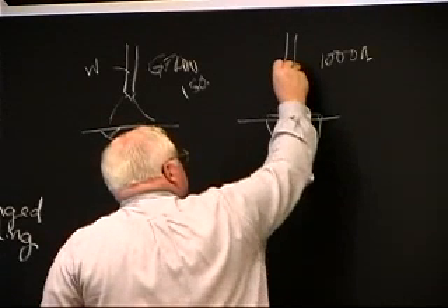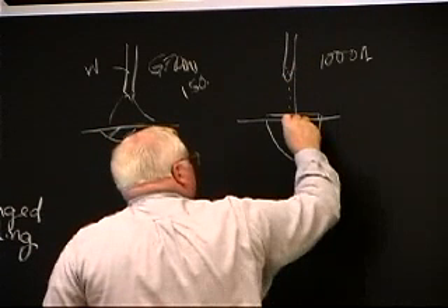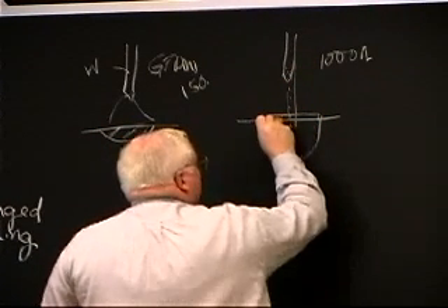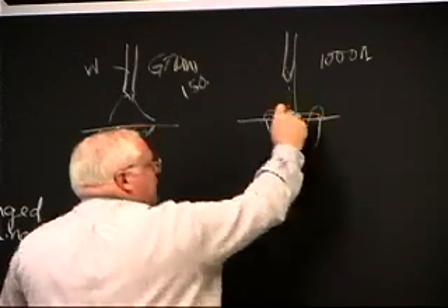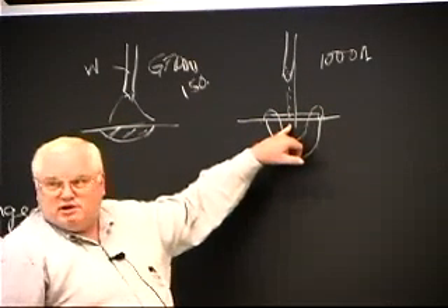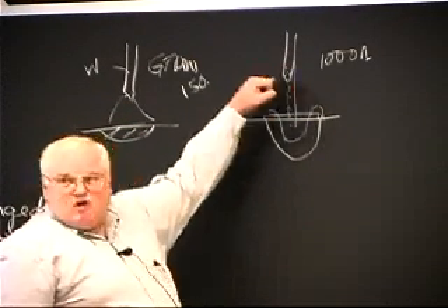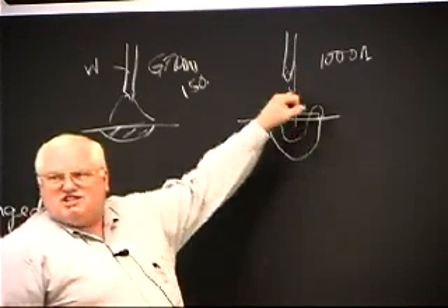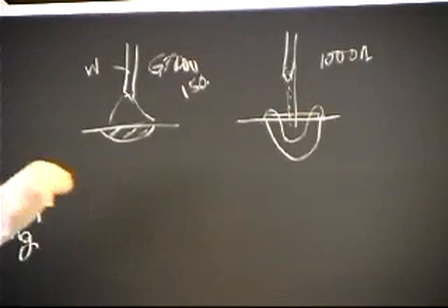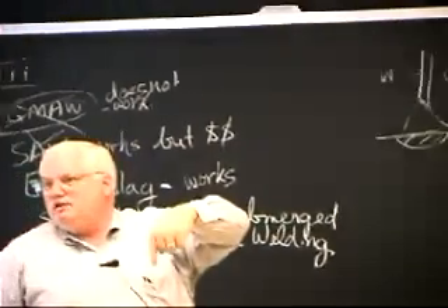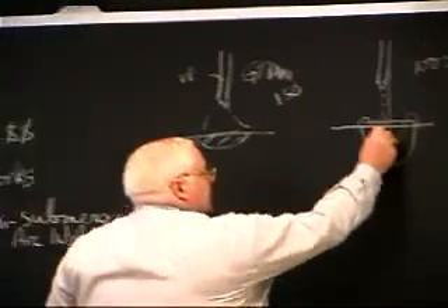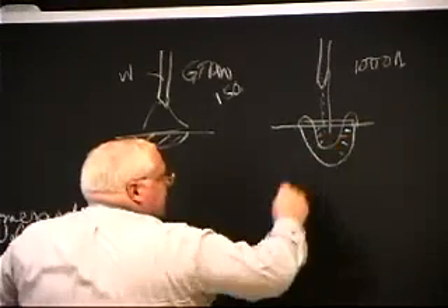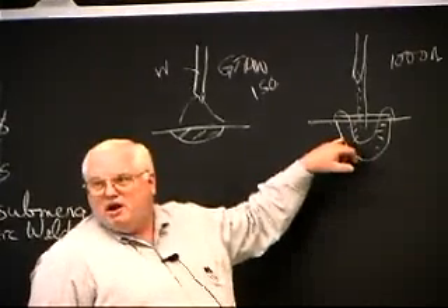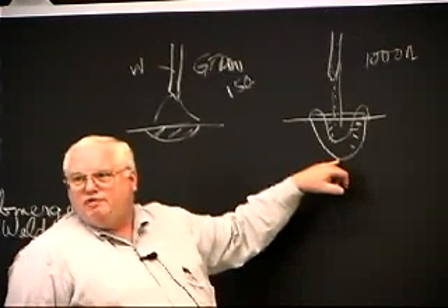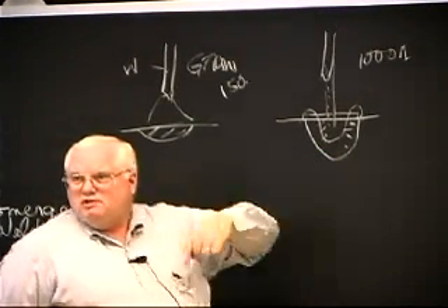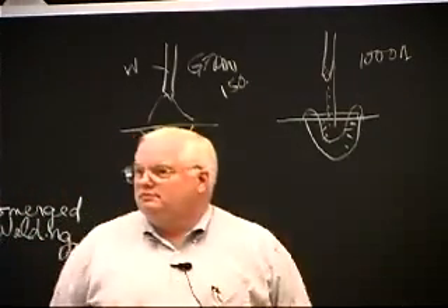If I actually take that electrode and I might start it on the surface, but when I get going, this weld pool will be depressed. There's a force of the arc that depresses the surface, and I actually then now drive my electrode beneath the surface. So what's semi-submerged here is the tungsten electrode is buried beneath the flat surface of the plate. And now I'm putting all my heat in. If you will, maybe I'm only getting a 1/4 inch of penetration, but I'm doing it a 1/2 inch deep. I'm basically plowing through the zone.